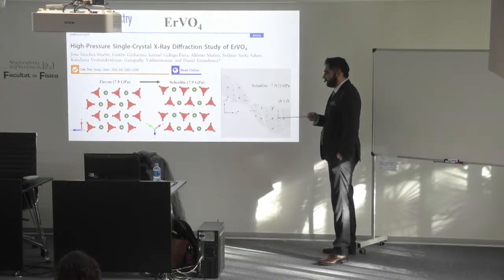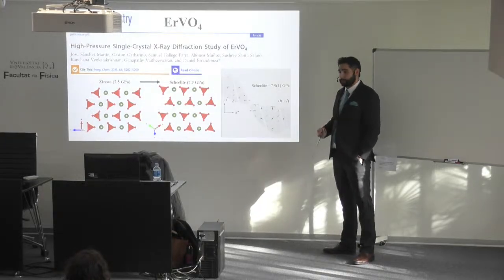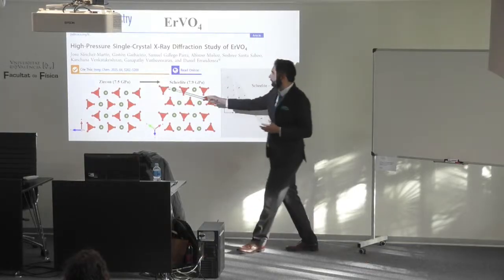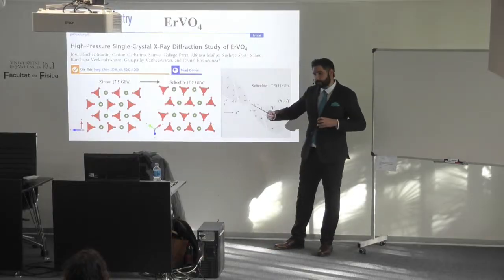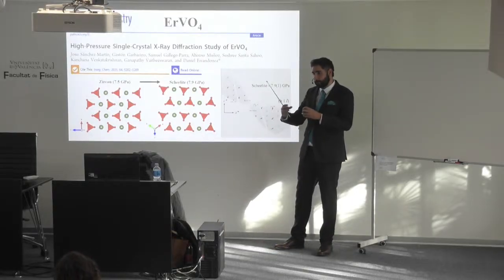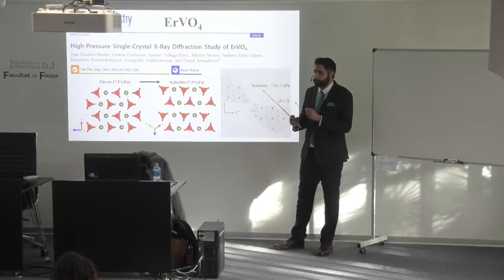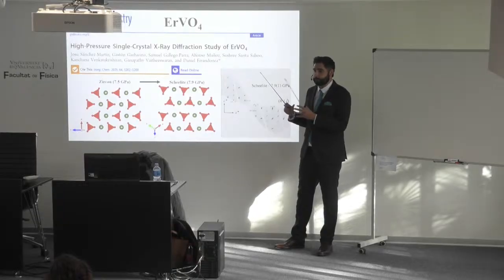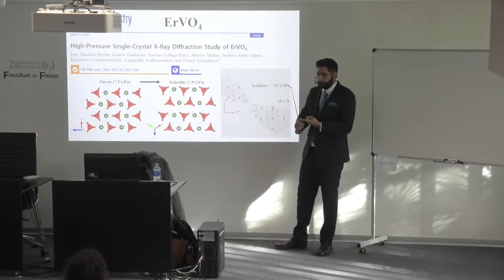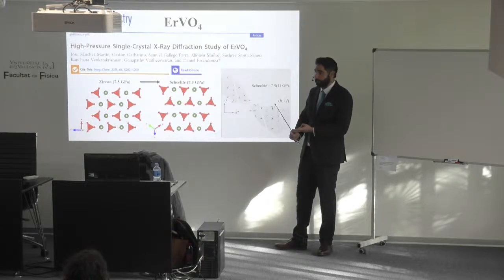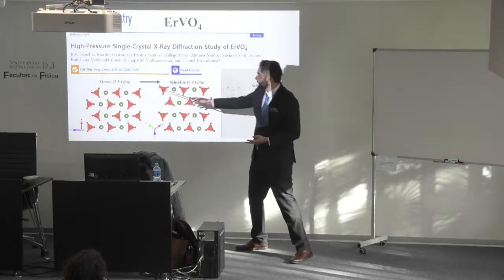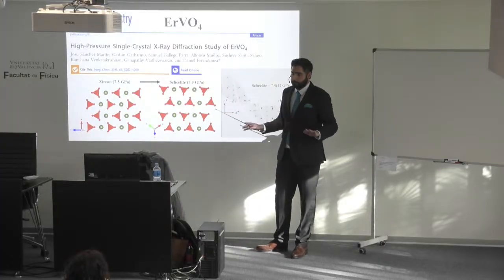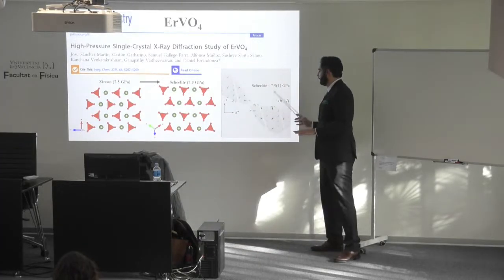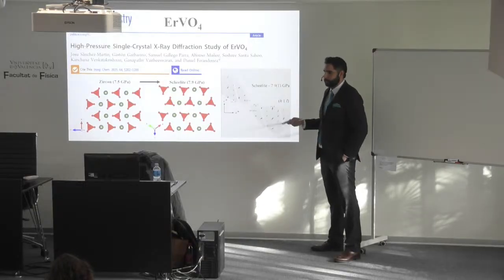Okay, so for erbium orthovanadate, in this case, we have some single crystal, and we also seen in the literature and our measurements that the phase transition from zircon to scheelite was sluggish. It was really extended in pressure. They were coexistent too much, and we thought maybe there's an intermediate phase in here that we are not measuring. Let's try to do this experiment the best as we can with single crystal and with helium as pressure transmitting medium. And what we saw is direct phase transition, no coexistence, and also the scheelite still being a single crystal.